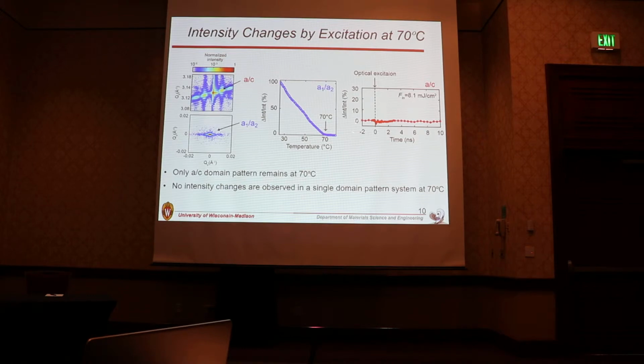And we did the same thing. We measured the total intensity change by optical excitation and found that the AC domain pattern intensity is not changed by the optical excitation, even with the larger optical fluence. These results support that these optically induced intensity changes can occur in a system with two different domain patterns, and the domain pattern transformation from AA to AC domain patterns is the origin of this intensity change.